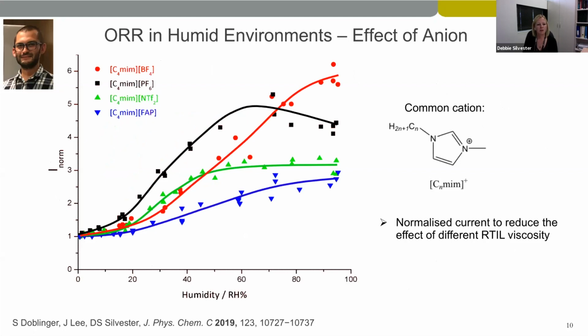What Simon did was to measure the current response, or the normalized current response, as a function of increasing humidity. The normalized current response here is the current response at a particular humidity divided by the current response in the dry environment. And we did this to reduce the effect of the different ionic liquid viscosities.